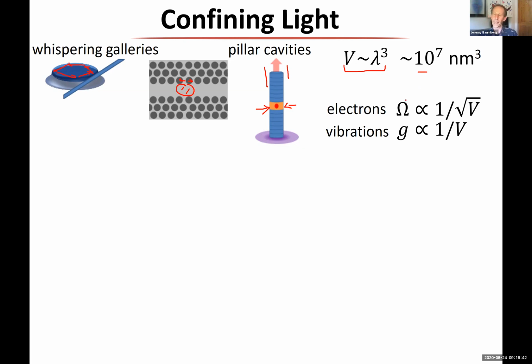And more technically, the issue is because the interactions with electrons or with vibrations or other parts of a system, a molecule system, say, they go as some power of 1 over the volume. So for instance, the light matter coupling with electrons goes as something like 1 over the square root of the volume. Or with the vibrations, it goes as something like 1 over the volume. So this volume here means that these interactions are rather small, so they're hard to look at. So if I want to look at one at a time, that becomes difficult.